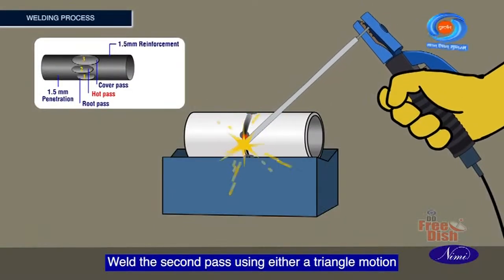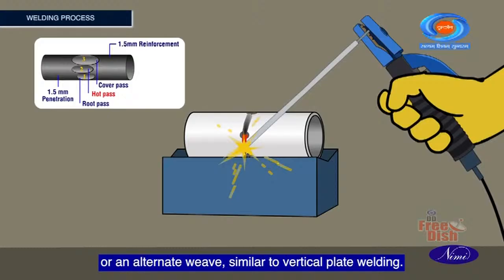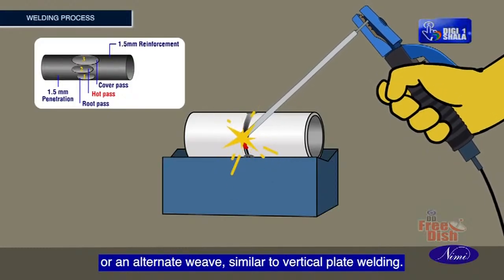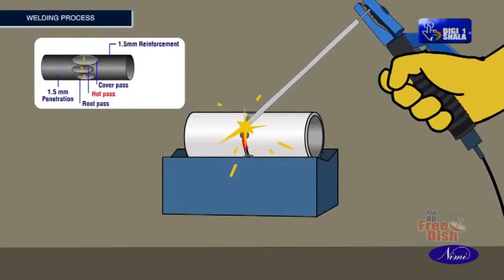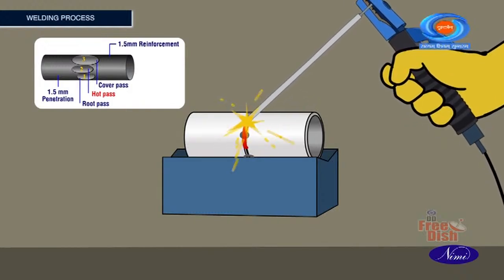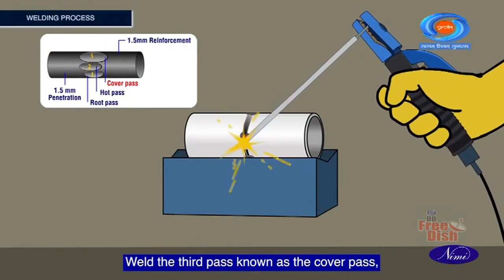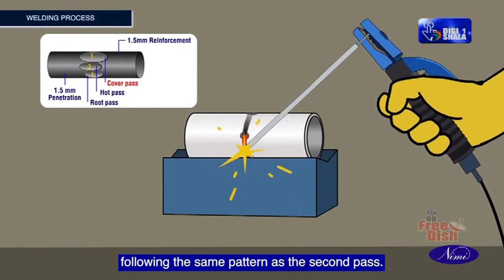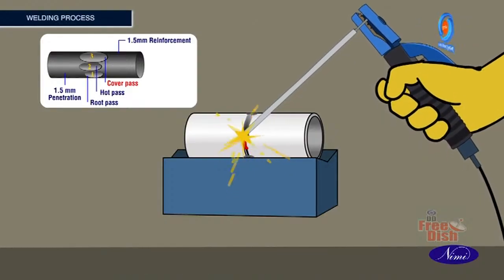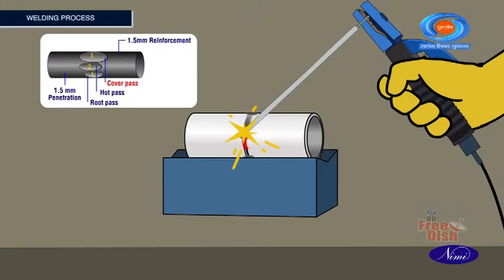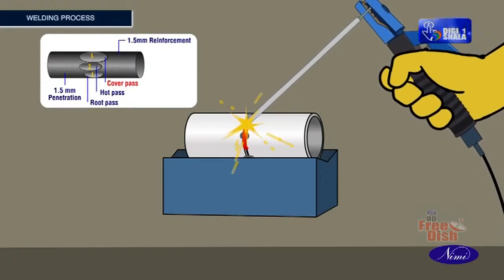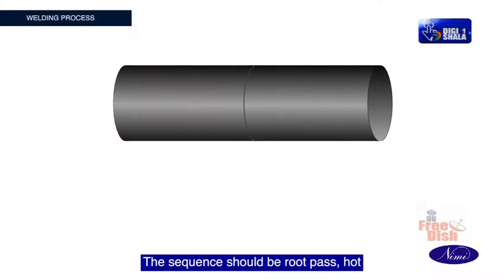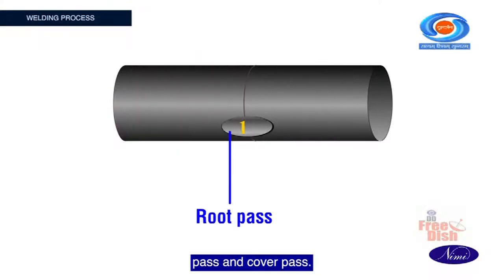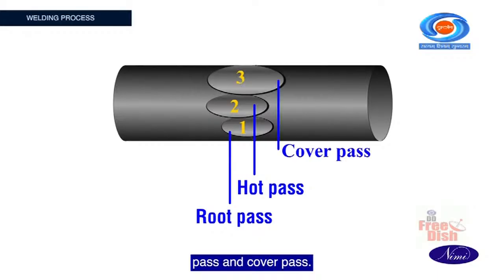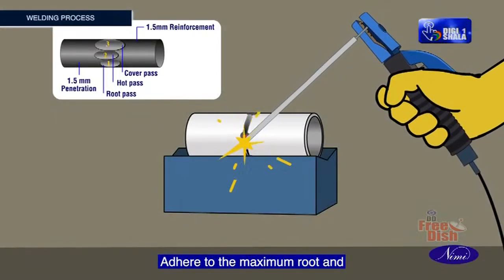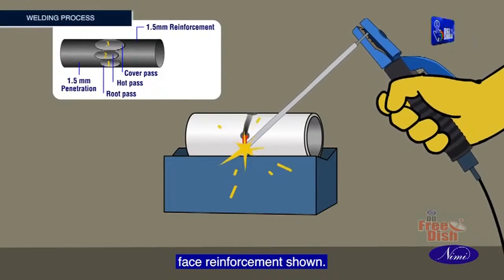Weld the second pass using either a triangle motion or an alternate weave, similar to vertical plate welding. Weld the third pass, known as the cover pass, following the same pattern as the second pass. The sequence should be root pass, hot pass and cover pass. Adhere to the maximum root and face reinforcement shown.